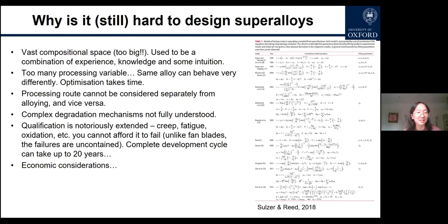And of course, qualification of such an alloy is not easy because you can't afford it to fail. The failures are uncontained. If they fail, then that means the plane is probably going to fail as well. So these qualifications are creep, fatigue, and oxidation. These experiments can take at least days, and usually months, sometimes even years. A complete development cycle can take about 20 years. So this is a very time-consuming process. It's hard to make it very, very fast. Of course, now we have the economic considerations because you don't want your engine to work only once, but you actually want it to work 20, 30 years.